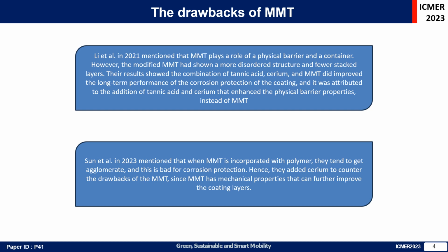and it was attributed to the addition of tannic acid and cerium that enhanced the physical barrier properties instead of MMT. Sun et al. in 2023 mentioned that when MMT is incorporated with polymer, they tend to agglomerate and this is bad for corrosion protection. Hence, they added cerium to counter the drawbacks of the MMT since MMT has mechanical properties that can further improve the coating layers.